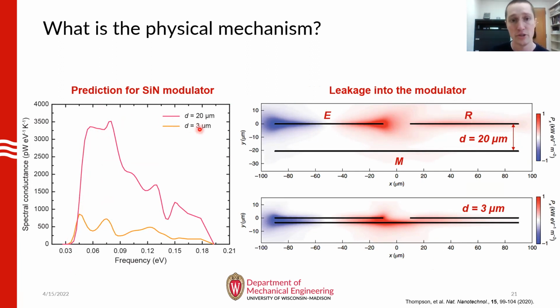Now when the vertical offset is reduced to around 3 micron, you get a suppression in the spectral conductance everywhere, but especially at that peak frequency of 0.075 eV. I want to draw your attention now to the plot on the top right. This is the computed spatial distribution of the Poynting flux in our three-membrane system. And I should note that this Poynting flux was computed at that single frequency of 0.075 eV.